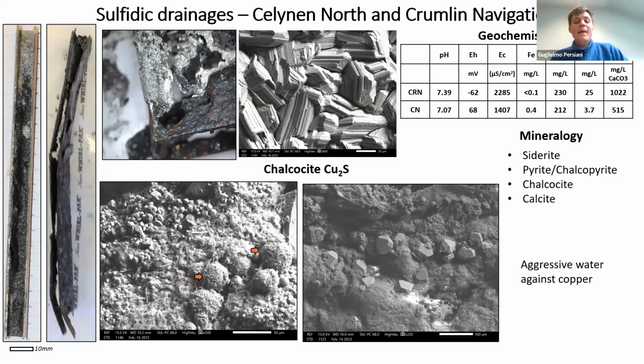And again, how they dissolved is probably that the copper just dissolved and then precipitated right after as chalcocite. So here we have a corrosion which is driven by hydrogen sulfide, which drives the dissolution of the copper in the first instance and then precipitates it out as copper sulfide. And this is very critical at this site, but I think those sites are rare. It's not common to find this kind of chemistry, but this hydrogen sulfide-rich water might be representative of the deep mine water, as already mentioned by Angela earlier. So those sites might represent a good case study, a good example of what we can expect in the most critical conditions of the chemistry of the mine water, right? So what we can expect.